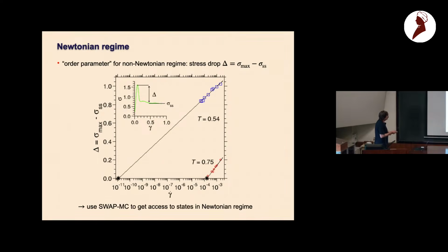We can do the same at 0.54, and then we are here, and then for over many orders of magnitude, we would land here at 10 to the minus 11, so an extremely low shear rate.